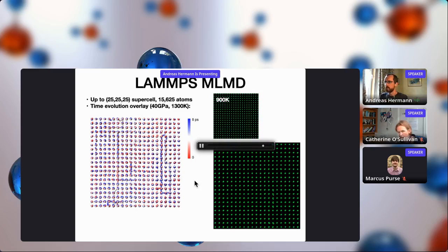I'd like to show you here the simulation of the solid, where you see absolutely nothing because everything is on the lattice sites. And here at 1300 Kelvin, you can see now the dynamics. You can see these little snakes of atoms moving around. Everything gets started by a Frenkel defect evolving in the system somewhere. Somewhere in this simple cubic lattice, a calcium atom will hop out of the lattice site, and that will pull along a whole chain of other atoms.